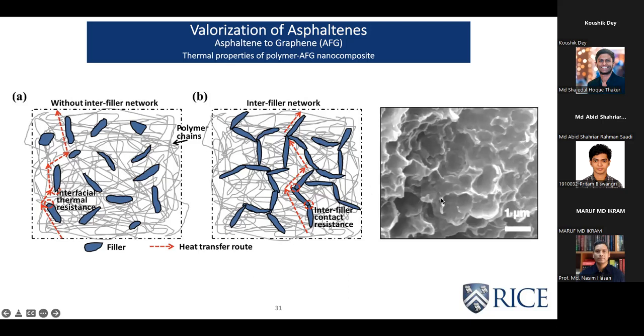This is again another AFM image of the surface of the 5-weight% composites. In 5-weight% composites, we often saw this type of graphene-like sheets stacked with each other, more like an interconnected network, which we did not see in 1-weight% or low-weight% composites. So maybe we speculate that these are those interconnected networks that we were talking about here.